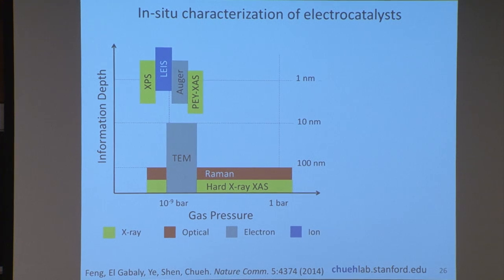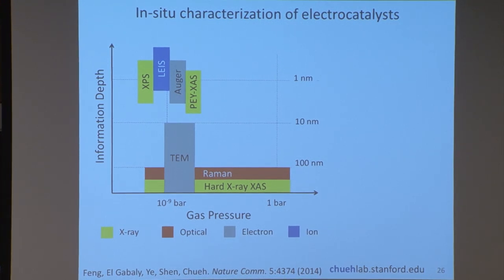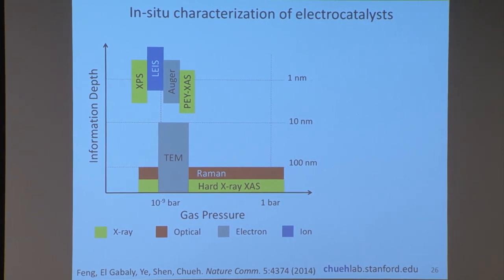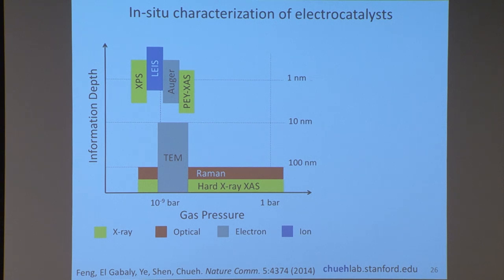The challenge thus far has been managing both the sensitivity to the active site. So after all, this is catalysis. So that means you have to be sensitive to the first few layers of atoms. This is the y-axis of the plot. The x-axis is the gas pressure. So these reactions happen typically at 1 bar. If you have to go to vacuum, which is often what we do to make these measurements, then you're not operating in the real system.